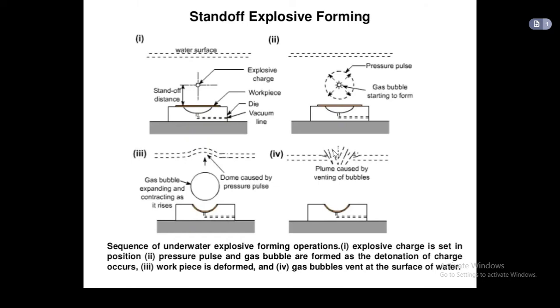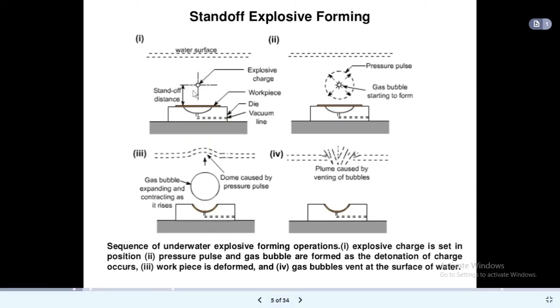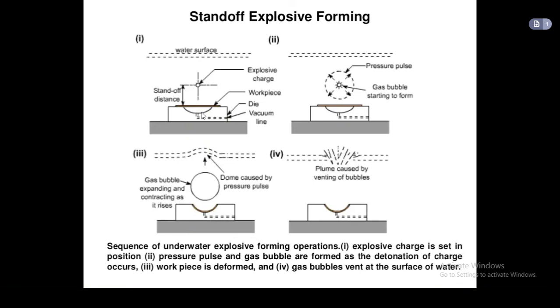So now we will discuss what this standoff distance is and how much distance is required. The distance from the explosive material to the workpiece is called the standoff distance, and it is generally taken as S. Suppose the workpiece has a diameter D, then S is equal to D.